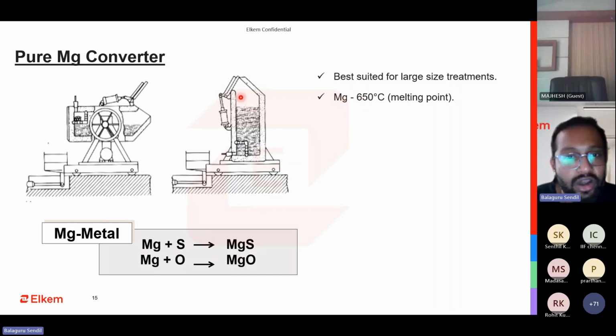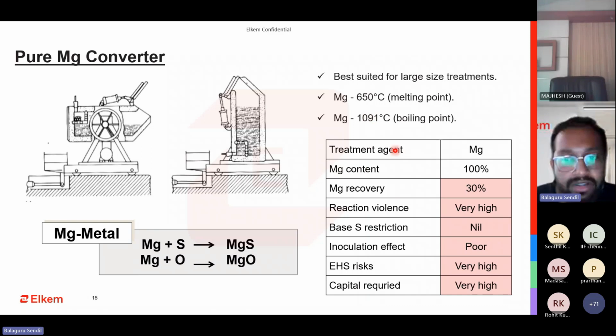You are going to pour it around 1400 or 1500 degrees Celsius, depending upon how long you want to pour. But the magnesium starts melting at 650 and starts boiling at about 1090 degrees Celsius. So the reaction fumes will be very violent. What happens here is that the magnesium content, or the purity here, is 100%. The recovery is extremely low because the reaction violence is so much.